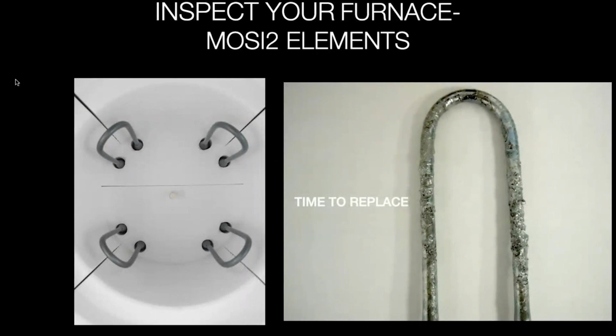These furnaces from VITA and most of these other ones use what's called molybdenum disilicide, which is a MoSi2 element. The picture on the left shows a fairly new furnace. I just stuck a mirror in there and photographed mine. And then I had to go to a lab to look at their elements, and they had already taken them out, and this is what they look like, which means it's time to replace it. So the SiO2 silica is basically a coating that's around this molybdenum, and it's a glass coating which protects the molybdenum from oxidizing.